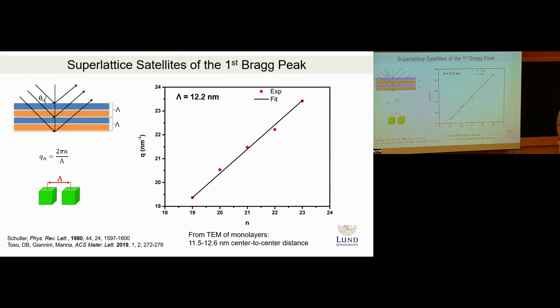Is there a sense for how thick the ligand layer has to be to see this effect? What you see in front of you? Yeah, so a single molecule is how thin the ligand layer should be in order to see this effect. I think it can be basically much thinner or thicker. I don't have a number for the upper boundary. As long as there is no disorder, you would be able to see this effect. But disorder would kill it, and I'll show how exactly.